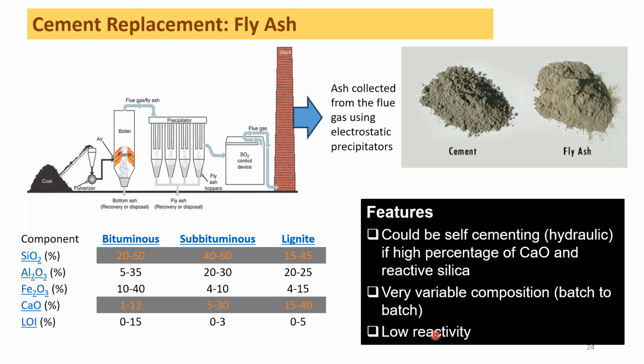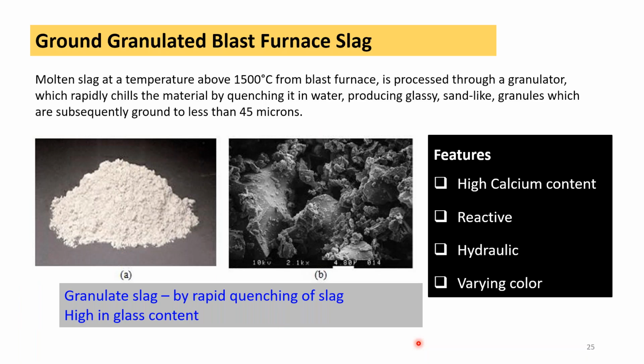But my bigger problems are that it is very variable in composition and it typically has a low reactivity. So when I replace cement with it, I have to expect the overall reactivity of the system to go down. Now, the ground granulated blast furnace slag is another waste that comes from the steel industry. It's basically the gunk that floats on top of the molten steel, that is cooled down very rapidly. It's quenched very quickly, and what we get is something very glassy and very reactive because of the quenching process. And we find that it typically has a high calcium content.